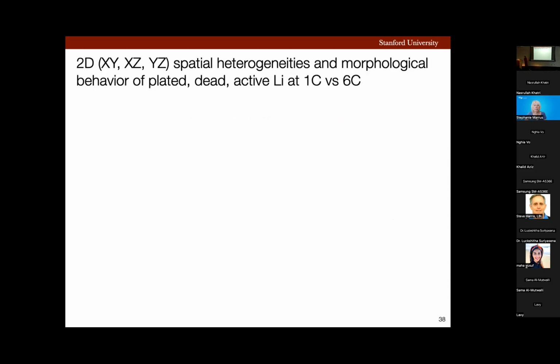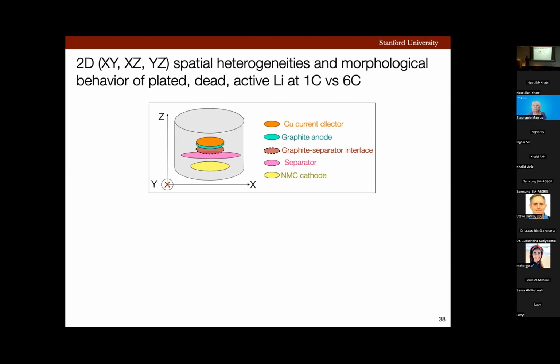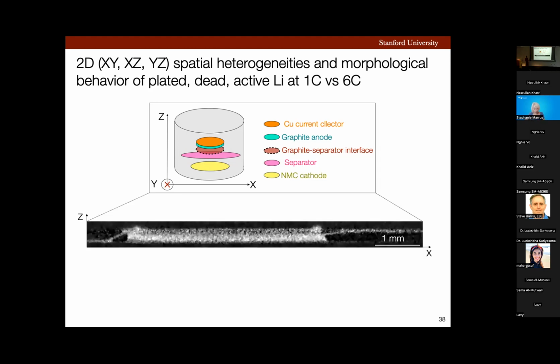Now let's look at these spatial heterogeneities in 3 planes in 2D: XY, XZ, and YZ. But before we do that, let's revisit the battery schematic. We have a current collector, graphite anode, interface separator, and NMC. And this is the corresponding cross-sectional XZ image of the battery, where we have anode at top and cathode at bottom, and separator in the middle. Now, I only used data that corresponds to the slices corresponding to the blue rectangle here, because lithium is only plating at the interface, and that's what I care about, right?